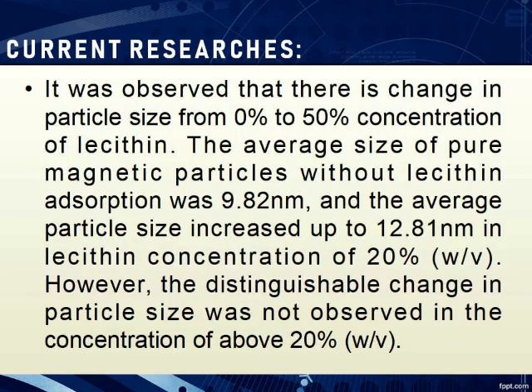It was observed that there is a change in particle size from 0% to 50% concentration of lecithin. The average size of pure magnetic particles without lecithin absorption was 9.82 nanometers, and the average size increased up to 12.81 nanometers at a lecithin concentration of 20%. However, no distinguishable change in the particle size was observed at concentrations above 20%.